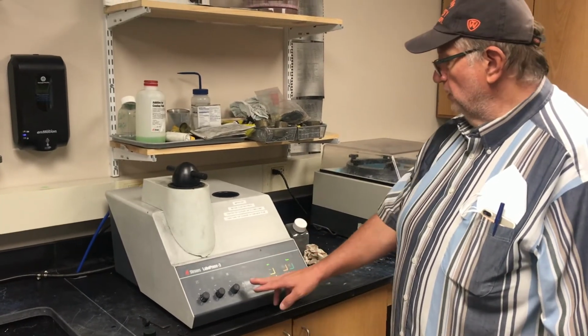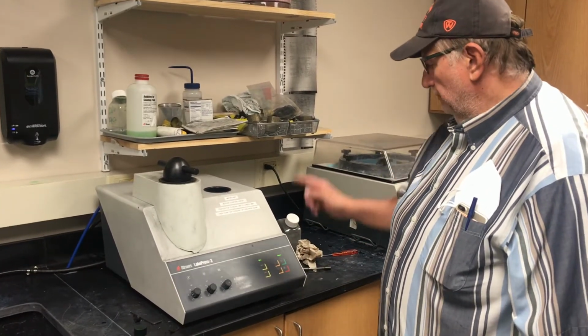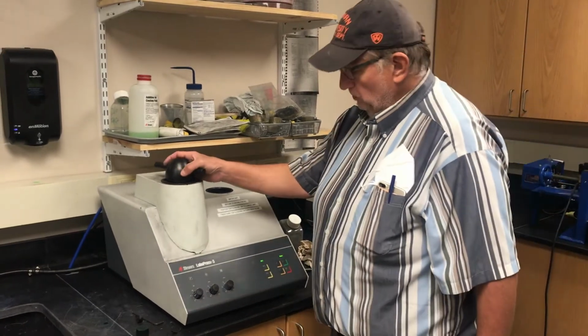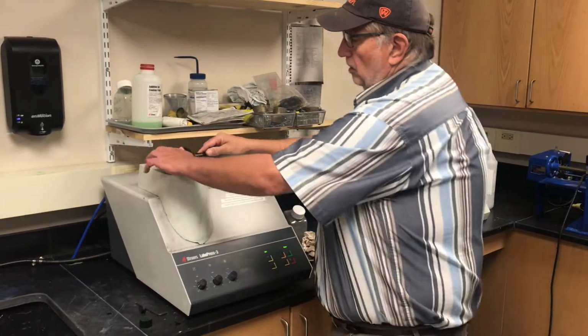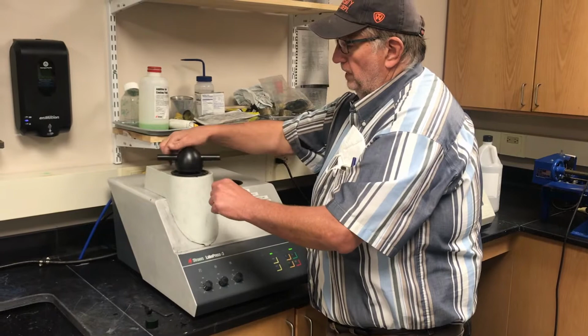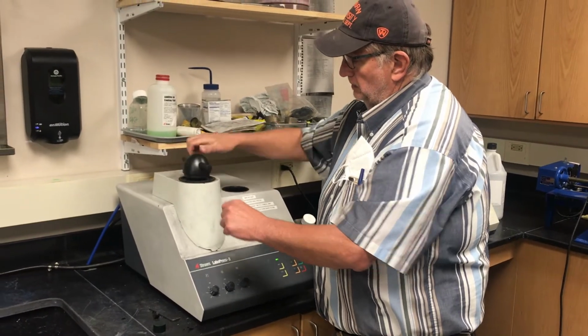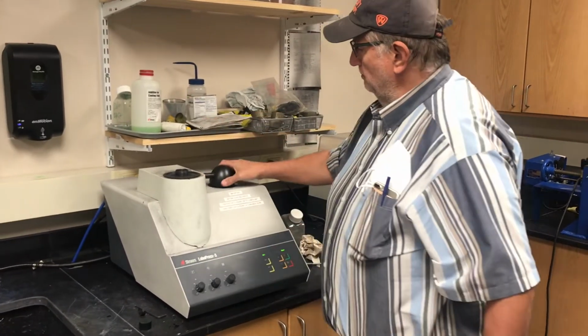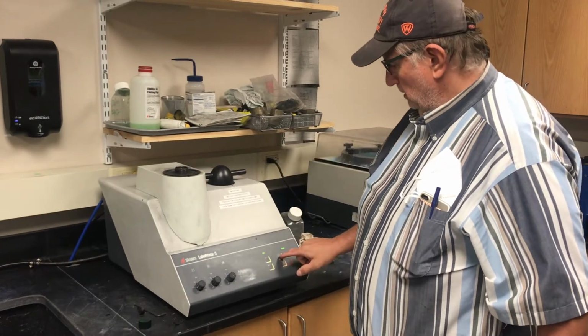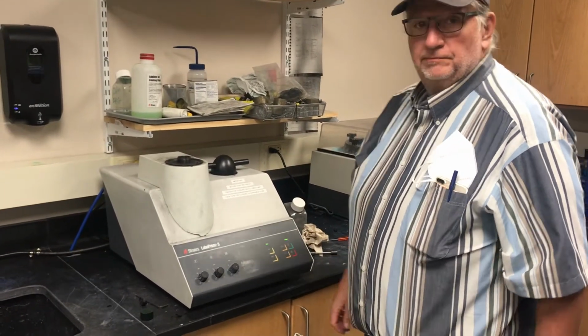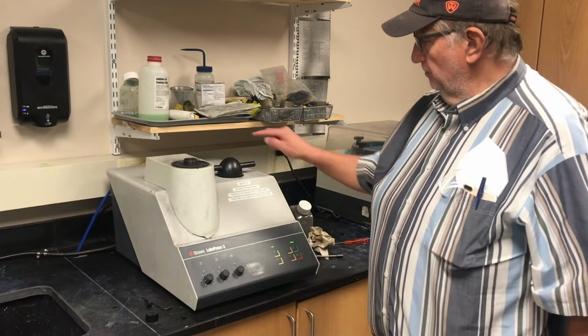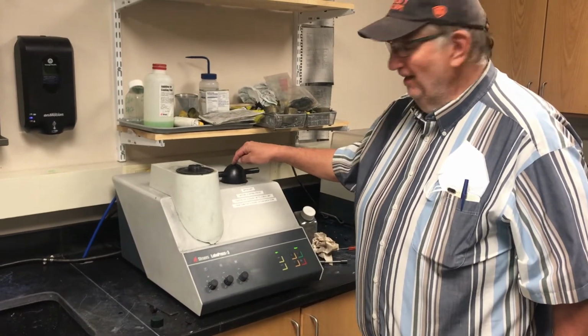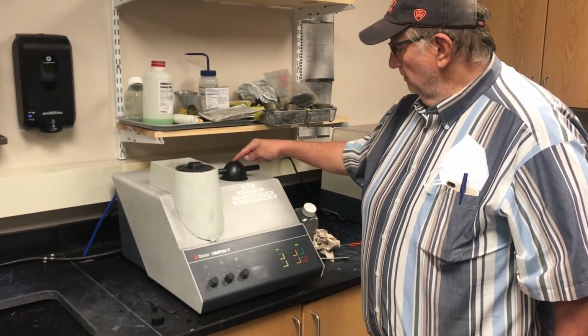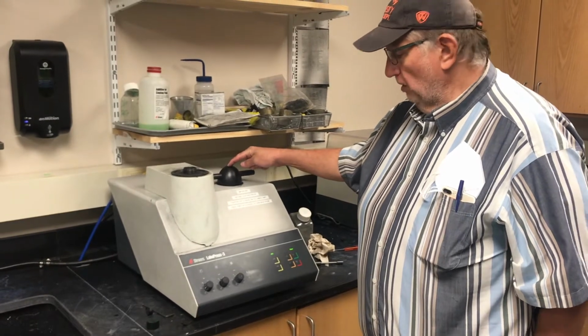When the cooling operation is complete, then the first thing you do is unscrew the cap, place it back in the holder, and raise your sample. Do not raise the sample before you release the cap. Too much pressure may cause damage to the machine.